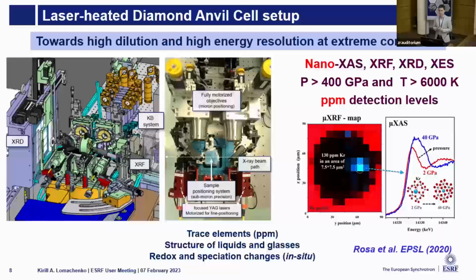Because if you want to compress it, it has to be very small. And if you want to be sure that you measure in a spatial region where the temperature achieved by laser heating is really homogeneous, you need a small beam. And also if your sample is diluted, and often it is, you need a high intensity. So you need the undulator source. So that falls precisely into the description of ID24.